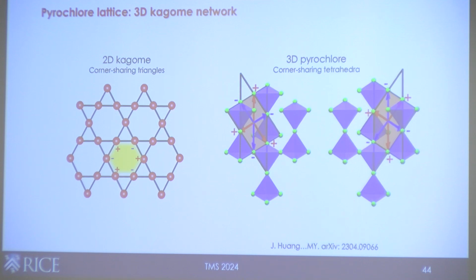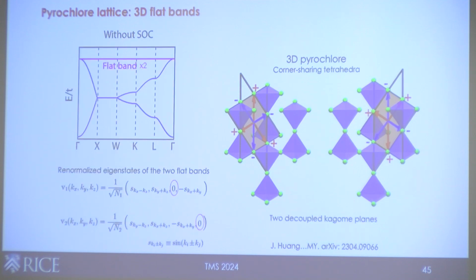So why would this give you flat bands? It turns out that if you calculate the linear amplitude, there are 4 sites associated with each tetrahedron. The site which is not contained in the Kagome layer has 0 amplitude, which means there's no hopping. Hopping is quenched even in the vertical direction, perpendicular to the Kagome planes. So what this means is essentially, from a tight binding perspective, we can consider the pyrochlore lattice as essentially 2 decoupled Kagome planes. And if you consider nearest neighbor hopping, the tight binding will give you 2 copies of flat bands, and then 2 dispersive bands. So this is what you would get, a flat band in 3D.